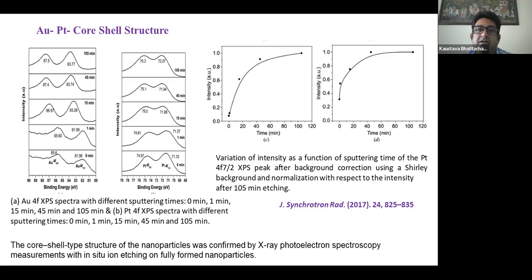This type of understanding is very strongly done for close Z elements. Here we did it for gold and platinum together. Post sputtering, you can see it was a gold core and a platinum shell. Platinum is almost constant as a function of sputtering, but the gold, as it is a core, increases in intensity with sputtering. If you check with SEM or TEM, it's very tough to tell about this type of core shell, and XPS can be strongly utilized.